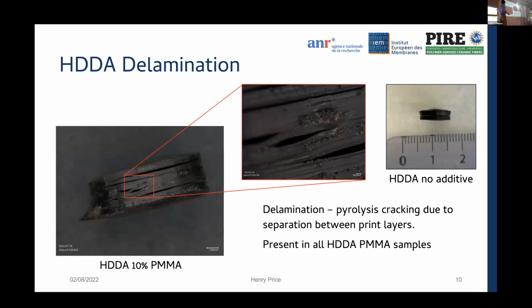Now moving to post-pyrolysis. Apologies if you can't see it so well. It did turn black, so it's hard to see on a darker background. This is a side view of one of the samples with 10% PMMA. I would like to call attention to these horizontal cracks, what I call delamination. This is separation between the actual build layers caused by the gas release during the pyrolysis process. This was consistent in all samples using this HDDA resin chemistry. Even with no additional PMMA, there is a crack all the way across the sample.